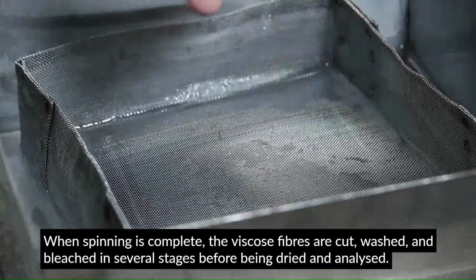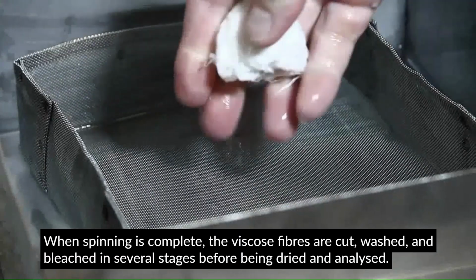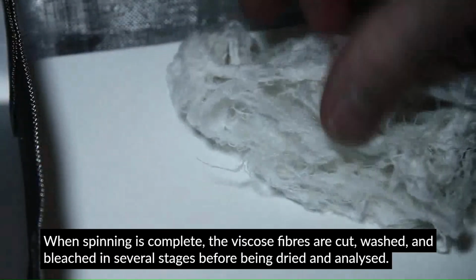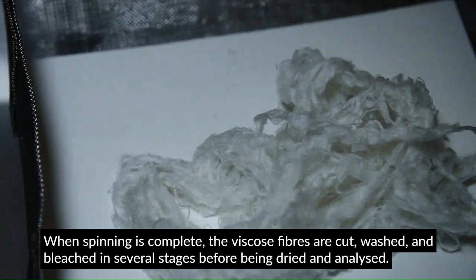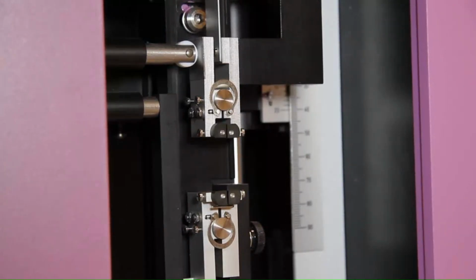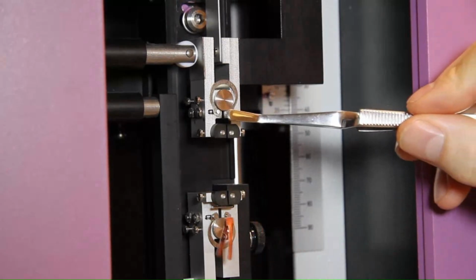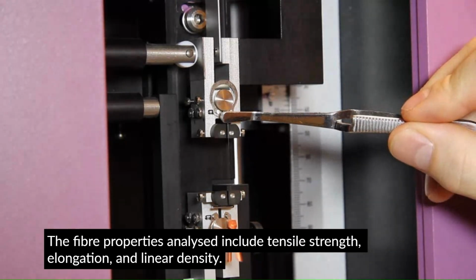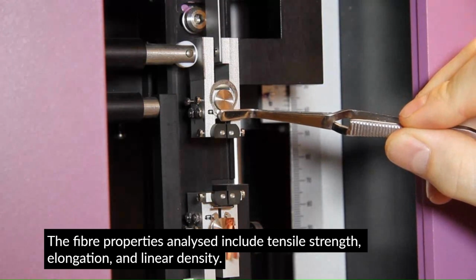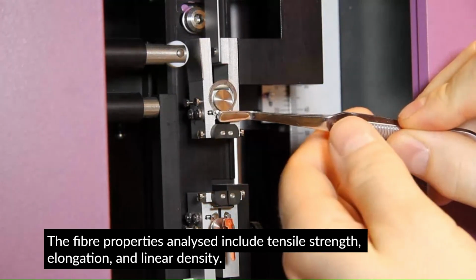When spinning is complete, the viscose fibres are cut, washed, and bleached in several stages before being dried and analysed. The fibre properties analysed include tensile strength, elongation, and linear density.